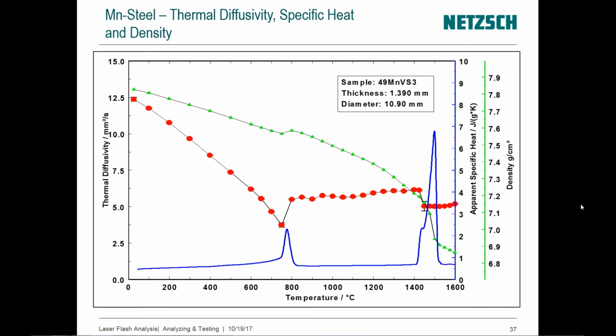Now, if the sample becomes far too thin, but you still want to measure the diffusivity with the LFA, you can use the in-plane method. We do that very often for very thin material. We use the in-plane component. At least you can access the radial component of the diffusivity in that case. If it's an isotropic material, that's fine, no problem. Otherwise, there might be some limitation depending again on the diffusivity of the material. And again, we are able to make some recommendation if you contact us.